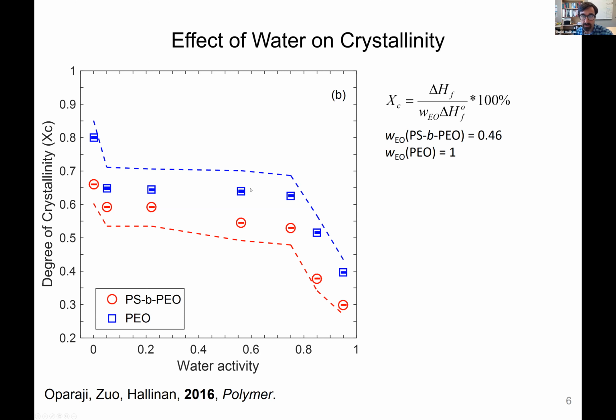The blue squares are the homopolymer polyethylene oxide, and the red circles are the block copolymer. You can see a couple things: as we increase the humidity, when we get to high humidity, the crystallinity decreases significantly, which was surprising to us—we didn't realize water could dissolve PEO crystals. The other thing you see is that the block copolymer structure itself, by confining the polyethylene oxide, results in, at any given humidity, a lower crystallinity.